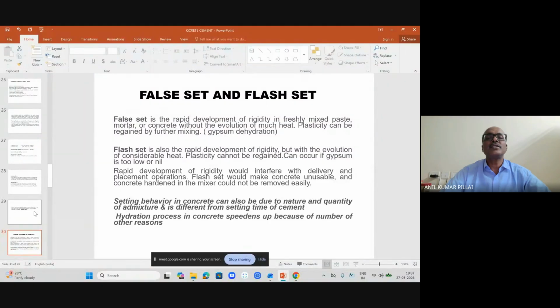Basically, what we have seen at practical sites, you will find these two terms, the false set and the flash set. False set is a rapid development of rigidity in freshly mixed cement paste, without the evolution of much heat, and plasticity can be regained by further mixing. So this is nothing to be alarmed about, but sometimes it may happen. And flash set is the rapid development of rigidity, but with the evolution of considerable heat. So plasticity cannot be regained as far as the flash set is concerned.